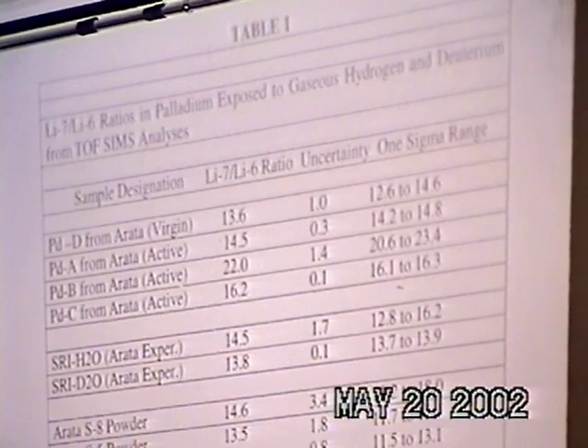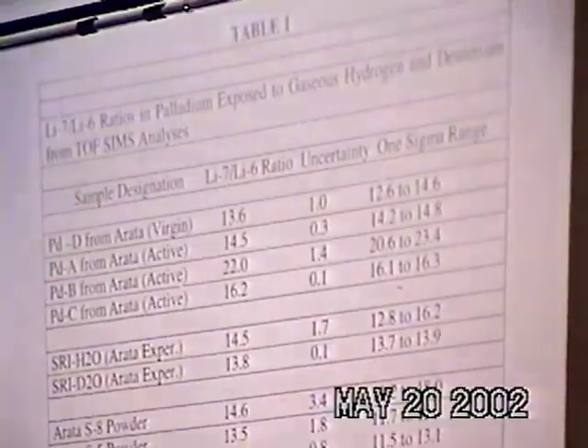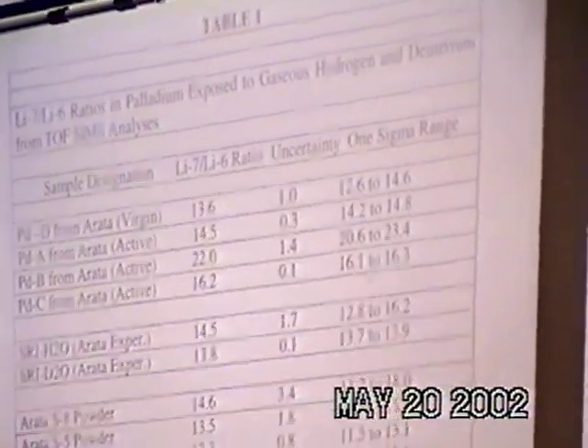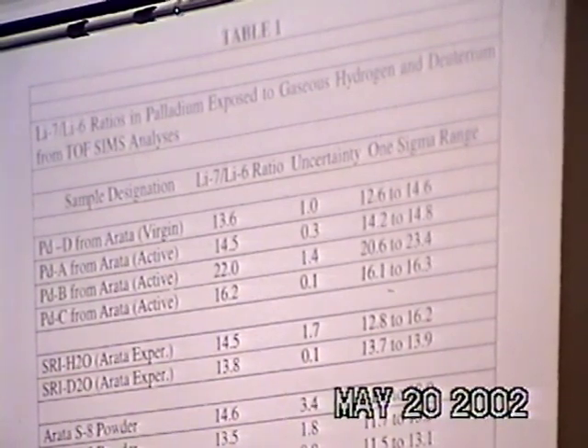The factor to increase, the big number, interesting. But I have a question. Sure. We used to measure the nuclear cross-section for the lithium and deuterium reaction, for the purpose of plasma and the particle interaction for hot fusion. And we know the reaction cross-section with lithium-6 and deuterium, we measure down to 100 keV. And we found the reaction cross-section is comparable for lithium-7 plus deuteron producing 2 alpha particle and neutron, and lithium-6 plus deuteron producing 2 alpha particle, just comparable. And in theoretical respect, I think the reduced mass for lithium-7 and deuteron reaction is a little bit larger than lithium-6 and deuteron reaction, about 10%.